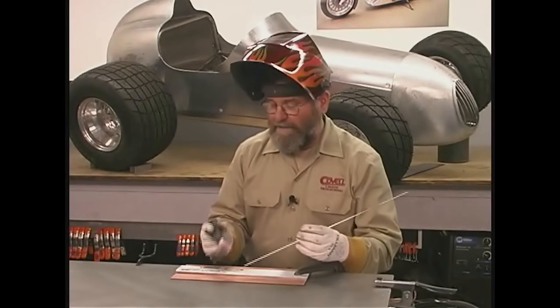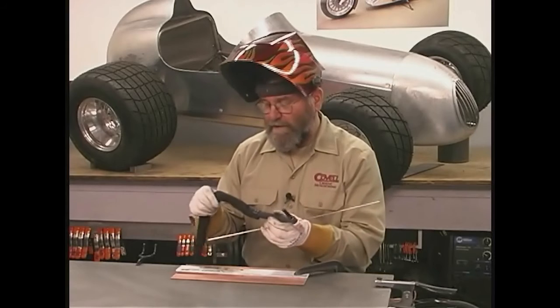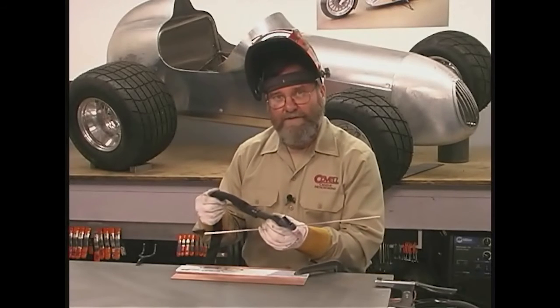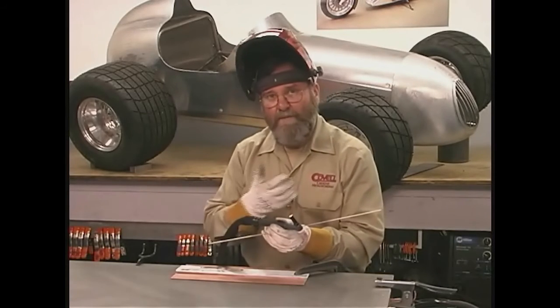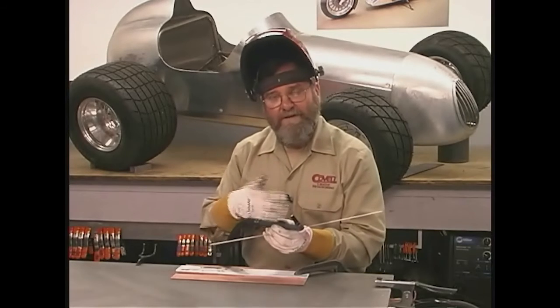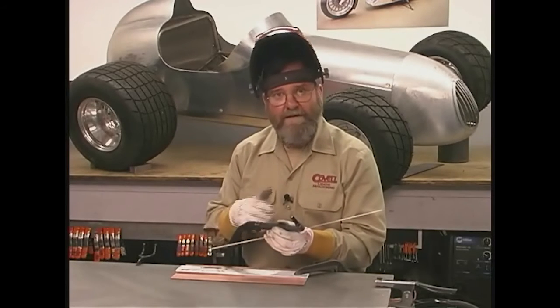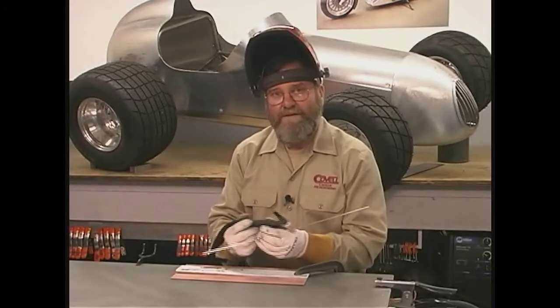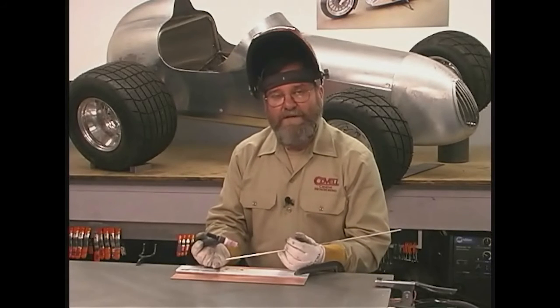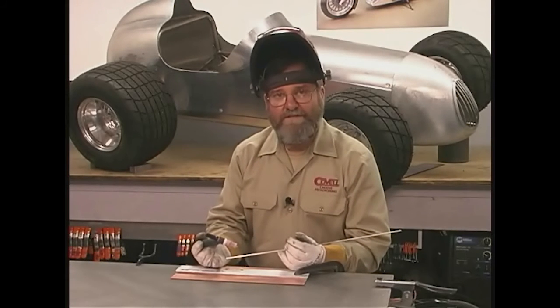Another thing that can happen is sometimes a little hole can be worn in the argon hose, and the hose acts like a carburetor, sucking oxygen or air into the argon gas, and that pollutes it. So check your system for leaks periodically. That can cause a problem too.